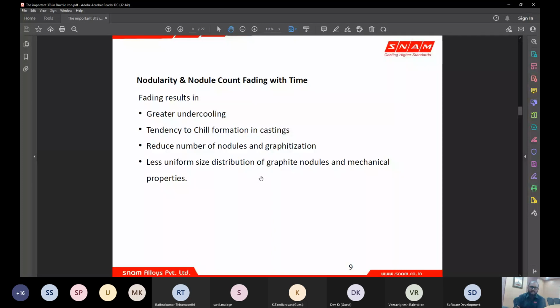And nodule count is again an effect of nucleation and the amount of nuclei present, which is inherently present in the liquid metal, and also added from your inoculation addition. So that is again time dependent, its efficiency. So these two are major important parameters, microstructural constituents, which decide your uniform casting properties. Nodularity, nodule count, and other microstructure constituents vary with time when there is variation in the time being measured in individual processes of production. So with this, we come to the end of discussing time.